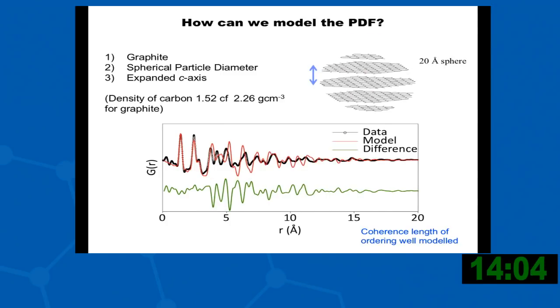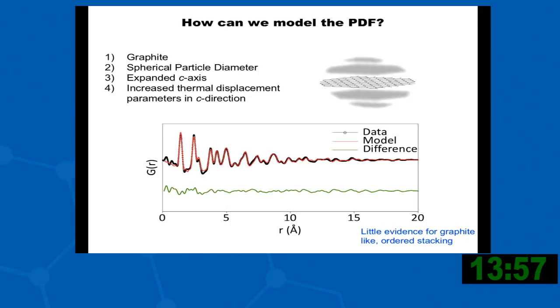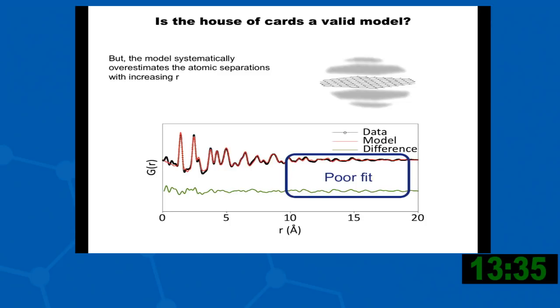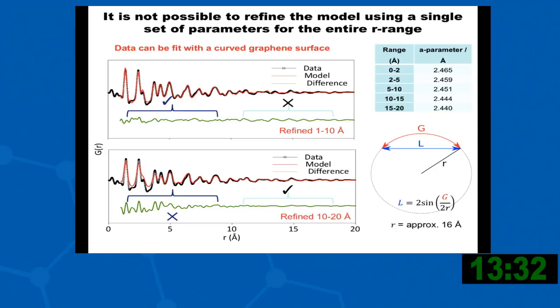So then let's think about increasing the spacing. We get some improvement to the fit, but it's still not very good. Then if we start to increase the thermal parameters in the C direction, so what we're doing now is basically creating disorder in the stackings of the layers, you can see that's a pretty good model for what's going on, but it's good here, while out there there's clearly some structural ordering that we're not capturing. And it turns out that the way we can model these structures is to look at curved surfaces. We can fit the data with one model at short distances, and then at long distance we can do it via curved material. What these measurements are telling us is that you have curved carbon or graphene sheets, and we could even extract the average radius of curvature of these systems.